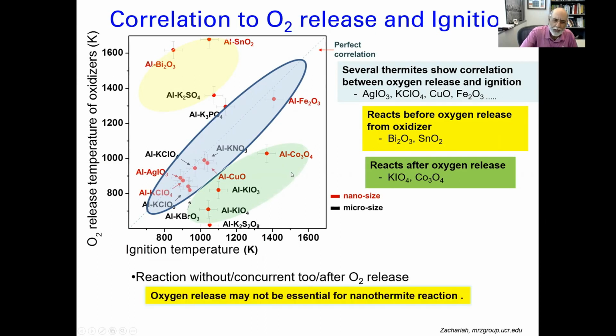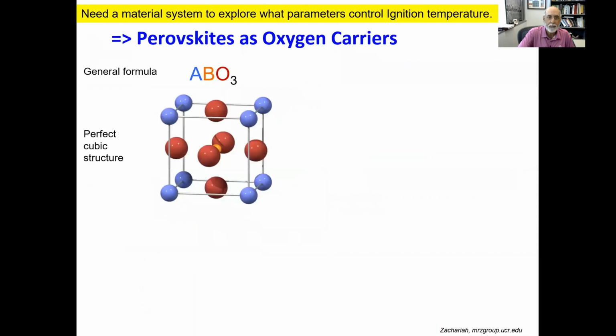So there's no real way of saying, oh, there is this correspondence between when oxygen comes out and when the system ignites. So we have to think about it in some other way. Certainly, this suggests that there's condensed phase processes going on. If the system is igniting at this temperature for bismuth oxide, but it has never released oxygen, it must mean that it's going on in the condensed phase. So we have to think about how that occurs.